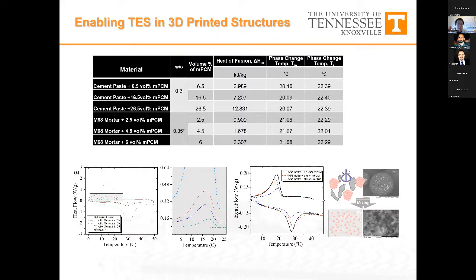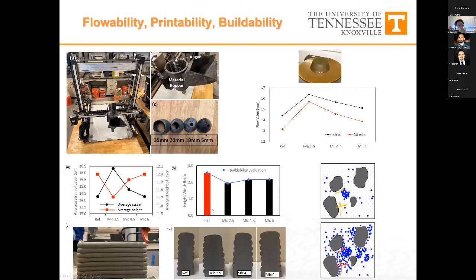One of the first things that we want to test is, based on the volume dosage, how much thermal energy it can store, not only to verify the functionality of the composite system, but also to verify that not a whole lot of particles or capsules get broken during the mixing and extrusion process. After that, we looked at how these functional additives impact the fresh properties, which include the flowability on the top, and the buildability and printability of the cementitious system based on different percentages of volume loading.